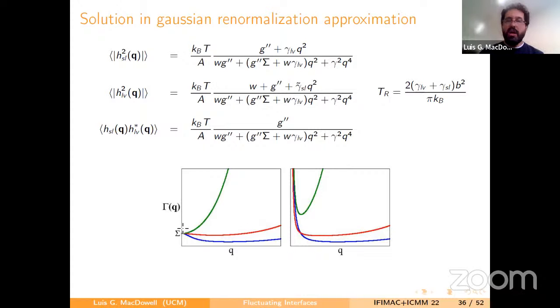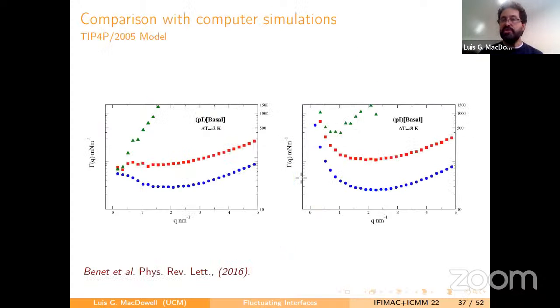So if you are above the roughening transition, where the interface behaves like a fluid, then you can write the spectrum of surface fluctuations, and you get that all of the fluctuations converge to a given point, which actually is the sum of the surface tensions, the sum of the liquid-vapor plus solid-liquid surface tension. However, if you are below the roughening transition, then effectively the surface tension is infinite and all of your surface fluctuations diverge. So we studied this problem actually from computer simulations.